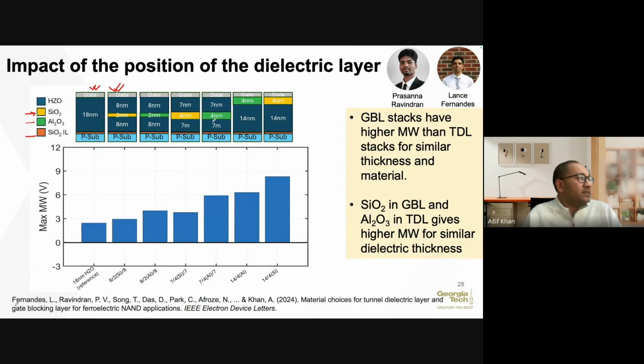And what we could clearly see is that depending on the thickness and the choice of the material, the memory window can change significantly, and there are significant opportunities to engineer the performance of this structure. For example, in this case, we saw that putting the ferroelectric material at the bottom and the dielectric material on the top gives rise to significant memory window enhancement. This was our initial structure that Dr. Das found, and then beyond that we started moving on, and we saw that as we move to the top we get a higher memory window.